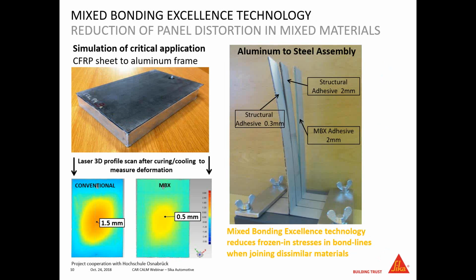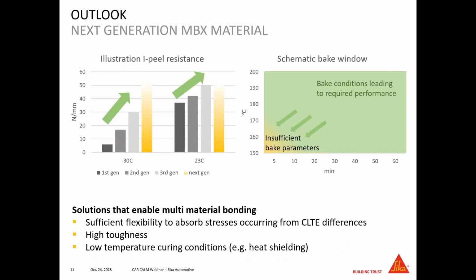Another example would be the T-peel samples here of bimetal assemblies. So these are steel aluminum parts or T-peel samples bonded with different types of adhesive, and you can see also here with the use of a structural adhesive and a thin layer, you have quite a high amount of stress leading to deformation of the sample. And if you're using an MBX adhesive at a thicker bond line, the deformation is greatly reduced. So you have less frozen in stress when you use dissimilar materials with an MBX material.